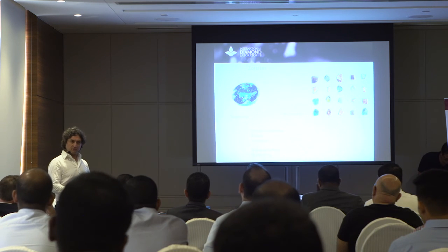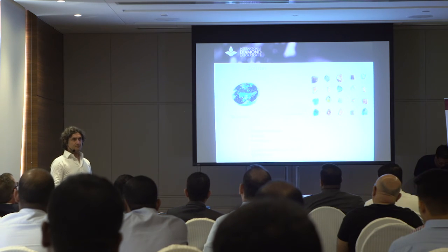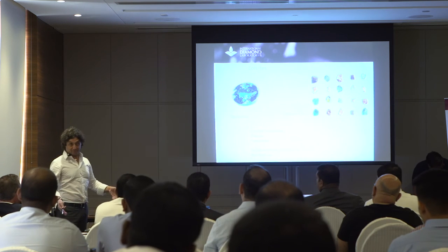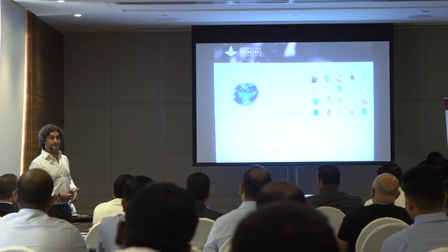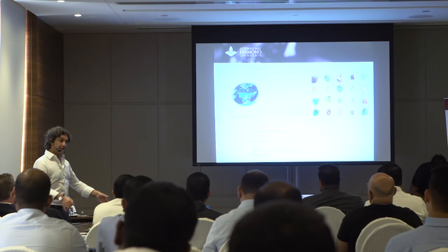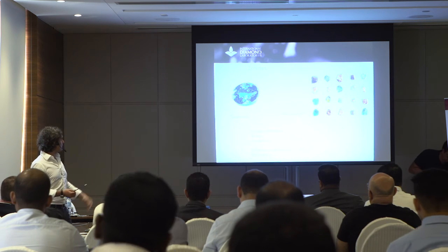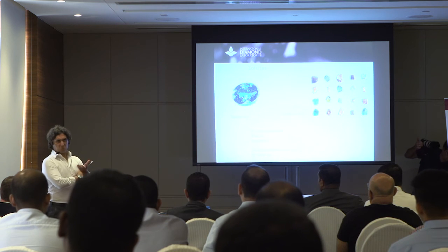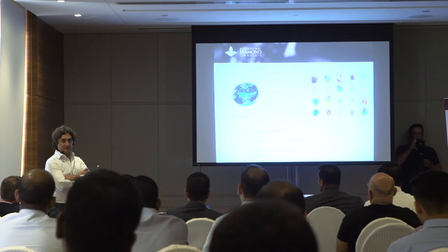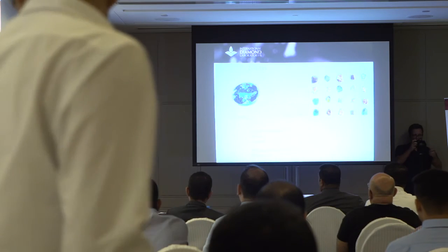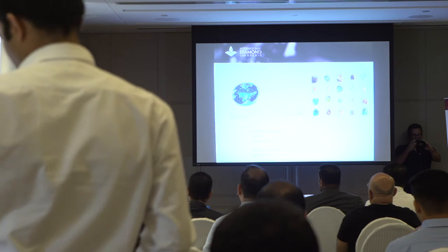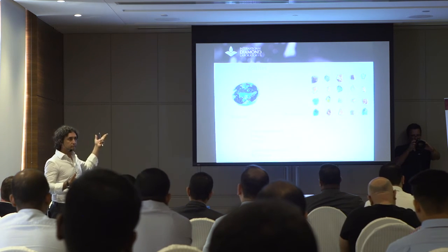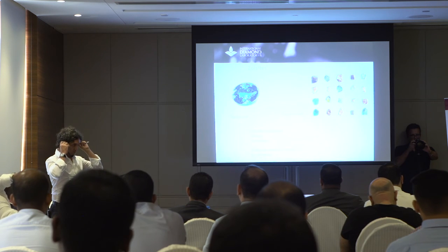So there is natural blue tanzanite. Probably it's a natural thermal process due to something deep in that area. Otherwise, they apply a low temperature, which means approx 500 degrees Celsius, and slowly heat the stone and modify the brown into the blue that we all know.